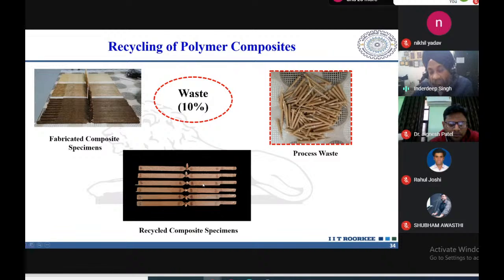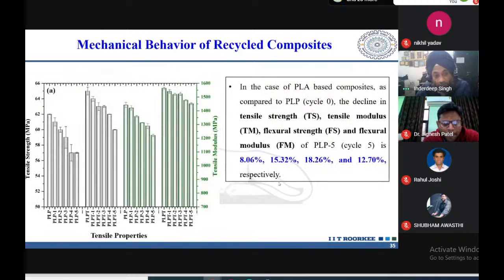So once we get a recycled composite specimen, again we can take this material from here. It has undergone a recycling, and again pelletize and granulate, use the granules to make the next series of samples, and again from there we can get this material as process waste, and again do the next recycling. So we have done this multiple times and established what the change in the mechanical properties is if we recycle it multiple times, and the results are there on your screen.